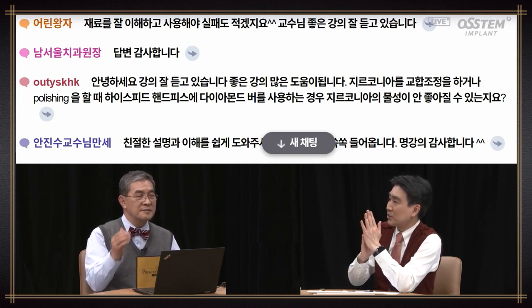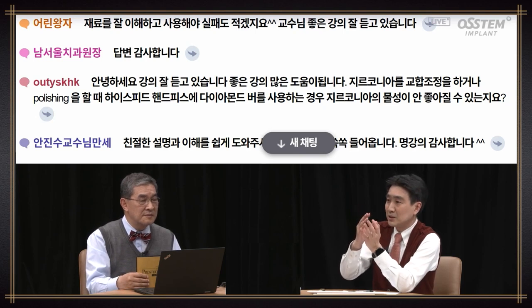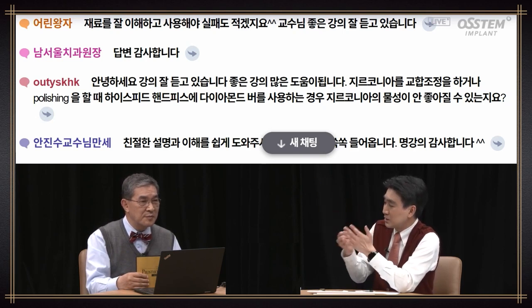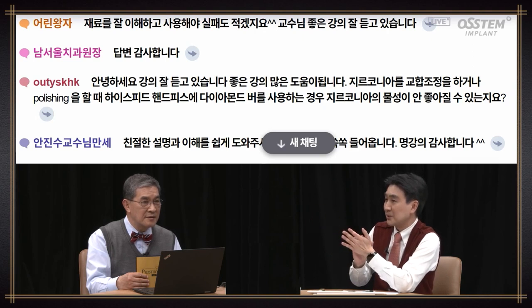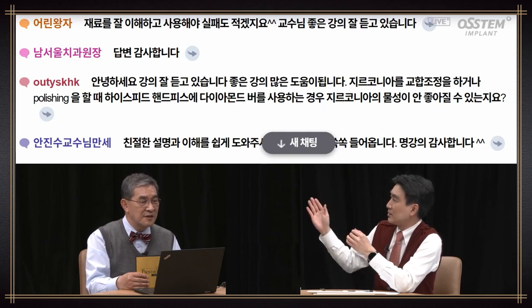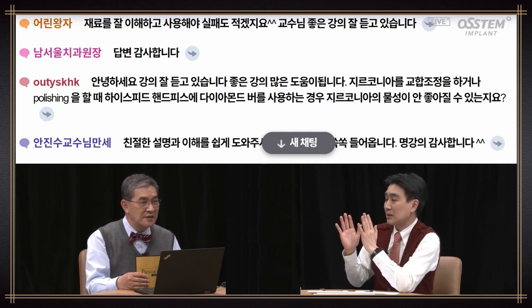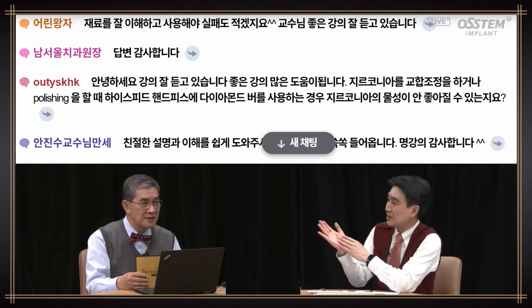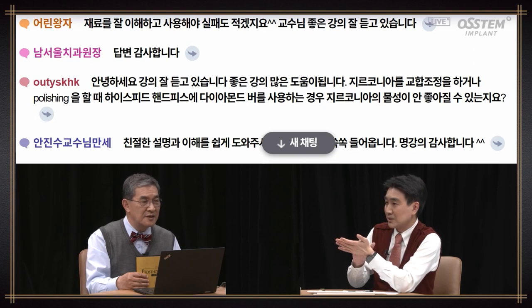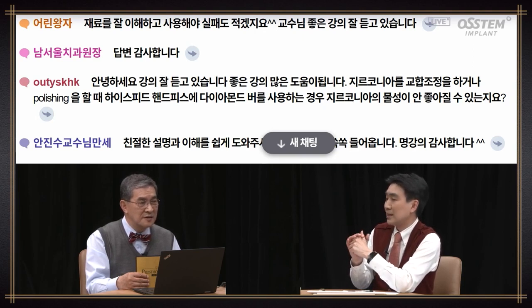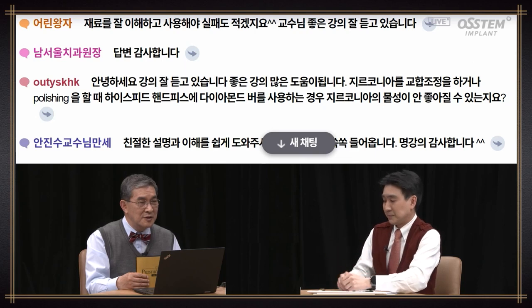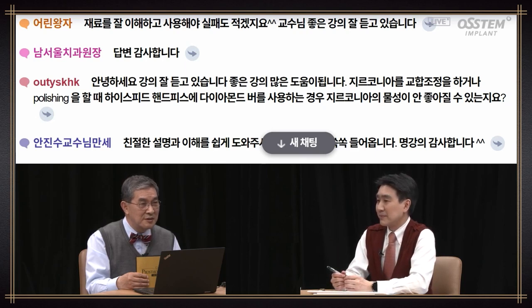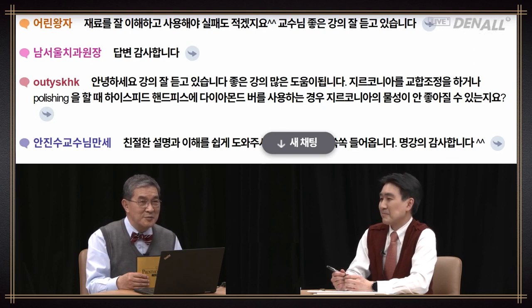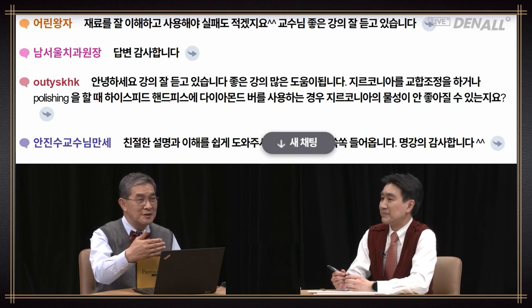If you look at the characteristics of zirconia, if you apply heat, even if you don't apply up to 2000 degrees, when you do polishing, it goes up 200 to 300 degrees. Even with that temperature increase, the phase can change. Therefore, grinding it off can accompany deterioration of physical property. You need to squirt some water when you do polishing. You need to be careful and be aware of the heat. In the case of occlusal adjustment, you need to cut it off a little bit. It's okay to cut the antagonist a little bit, but you cannot do that significantly.